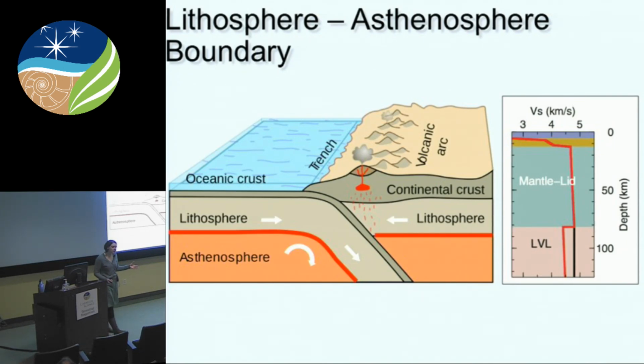But if this was true, then seismic profiles through this region should be gradual if it's only a thermal gradient. What we actually see in many studies is a sharp discontinuity, a lowering of velocity at this transition. What's often called upon is the presence of silicate melts aligned in large sheared sheets that help lubricate the overlying tectonic plates so that they can flow relatively unhindered over the convecting mantle.